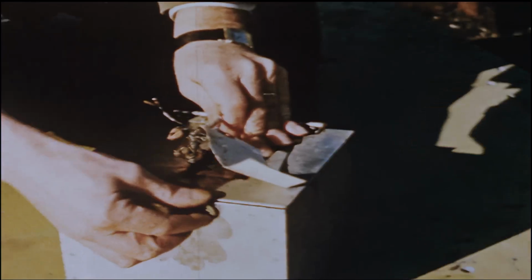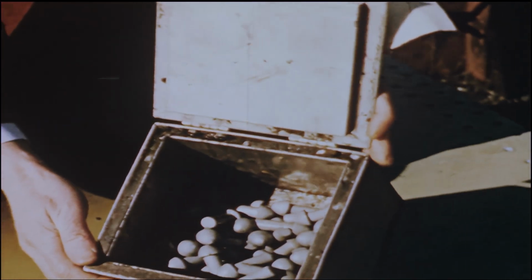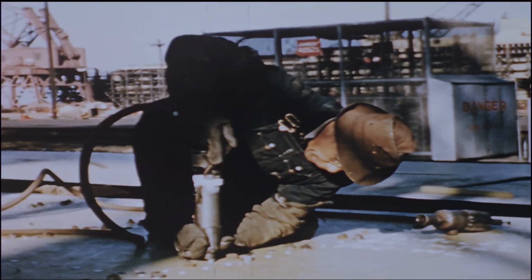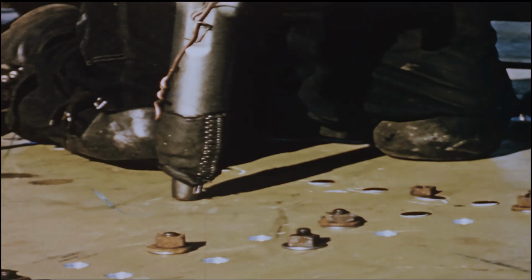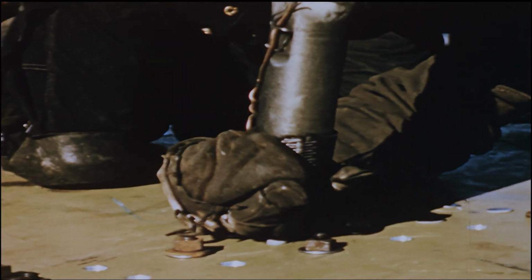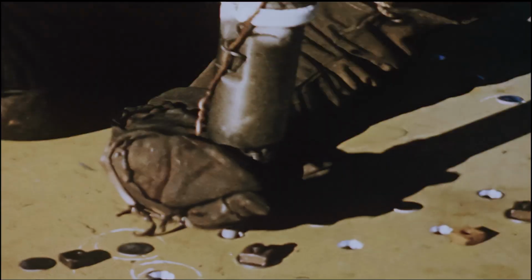They're delivered to the assembly areas in heat-insulated containers, because the special alloy from which they're made requires that after heat treating and quenching, they be kept at sub-zero temperature until driven. At ordinary temperatures, the rivets would soon harden, so that driving would be difficult. Driven cold in a soft condition, the working of the metal, together with the natural aging at outside temperature, will produce the design strength. The driving operation is fast, since it's not necessary to stop and chip each individual point when driven, nor to go back and harden up the point as on a steel rivet.